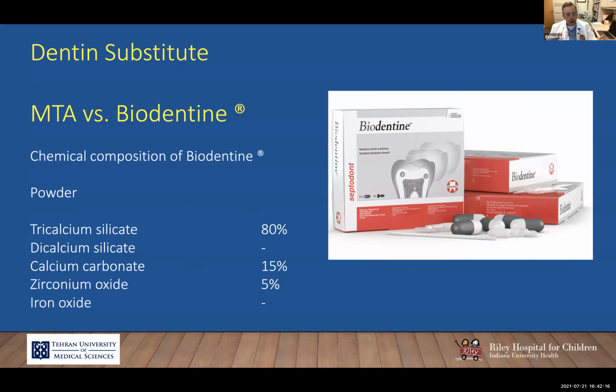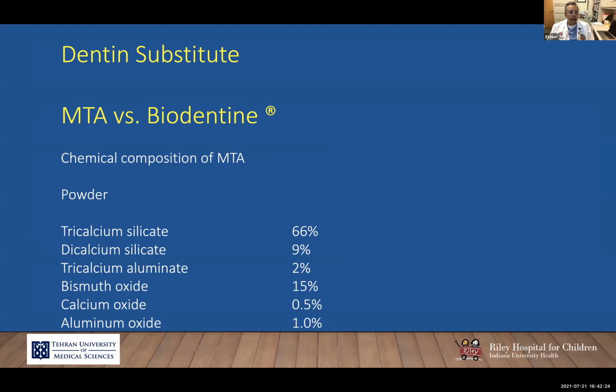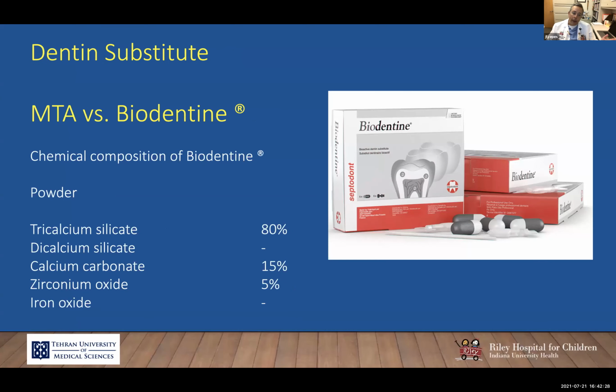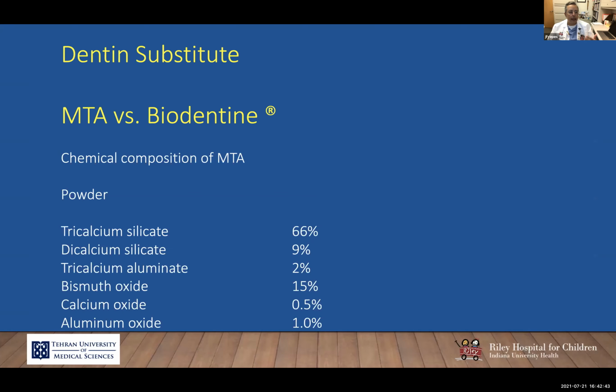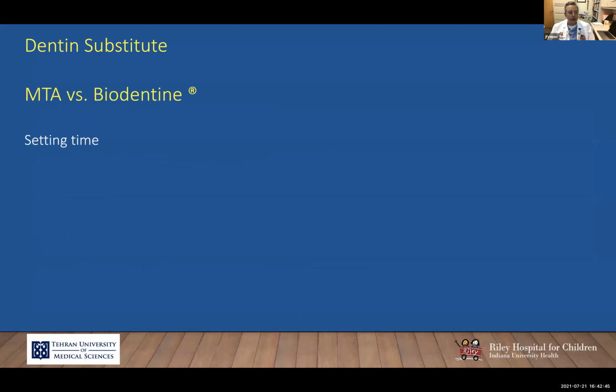So this is the chemical composition of Biodentin. The powder is basically 3-calcium silicate with other materials, is radio opaque. And this is the composition of MTA. So you can tell that if I go back, I hope that the slide is coming back. Pretty much the main difference between MTA and Biodentin is the amount of 3-calcium silicate. In Biodentin is about 80%, in MTA is 66%.